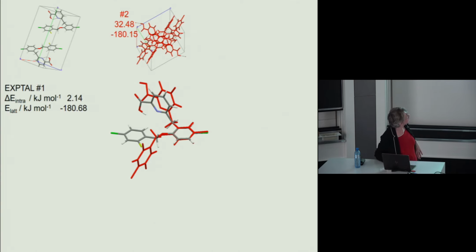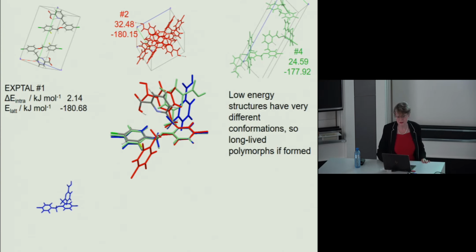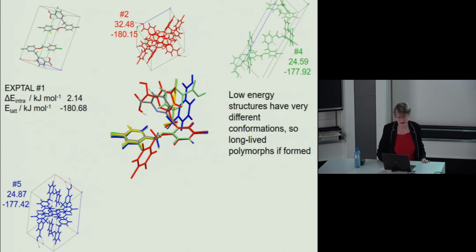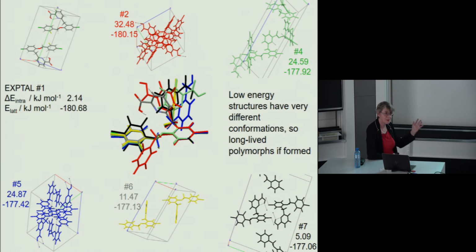But we found another structure which is hydrogen bonded, so the intramolecular energy penalty is high, but the hydrogen bonds mean that it's got virtually the same lattice energy. You carry on, the other hydrogen bonding conformation could also be found. Yep, we're generating quite a few different structures that are close in energy and have such different conformations that once you'd found them, it's plausible that it'd be very hard for them to transform back. So they should be long-lived polymorphs if you found them.